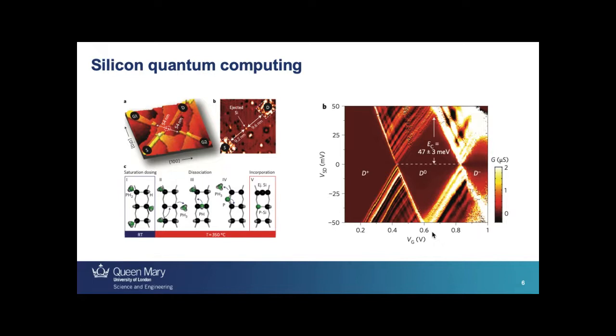So now what you're left with is a silicon surface, still completely covered, passivated with hydrogen, and only a couple of little holes in there where you've removed that single hydrogen atom. And then you can come in with a precursor gas, phosphine, which is a phosphorus with a couple of hydrogens around it. And this sticks to the silicon, but only where you've removed the hydrogen atoms. You can then heat it up a little bit. It gets incorporated into the structure. You overgrow it with a couple of layers of silicon, and you have your phosphorus atom sitting right where you want it with atomic precision.